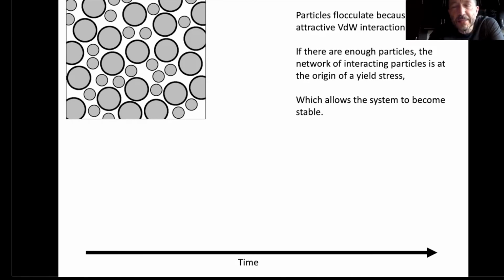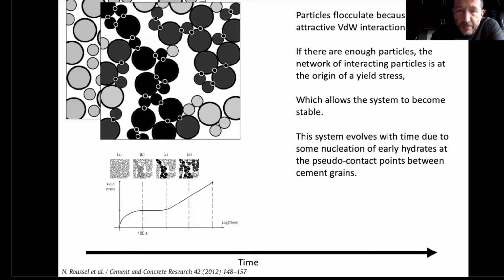However, we cannot forget that cement powder is a reactive powder. And even if we are in the dormant period and all chemical reactions at this stage are often neglected, it has been shown that there is a lot of dissolution and a lot of nucleation. And this nucleation happens at the pseudo-contact points between the flocculated cement grains. So as a consequence, in the first 10 to 100 seconds, the particles will flocculate through a diffusion aggregation process typical of colloidal suspensions.